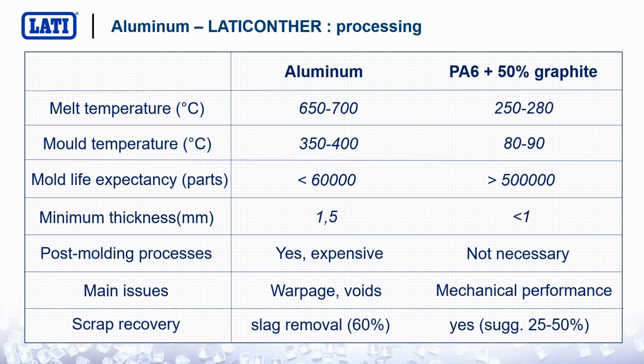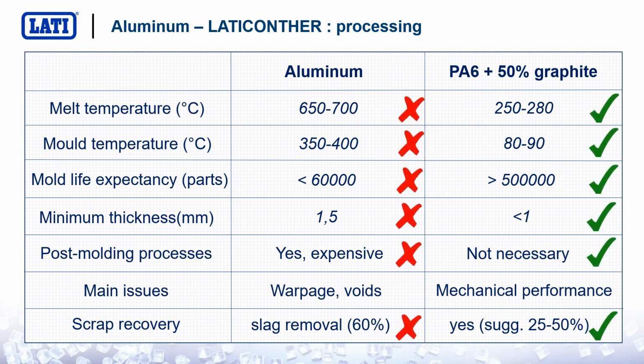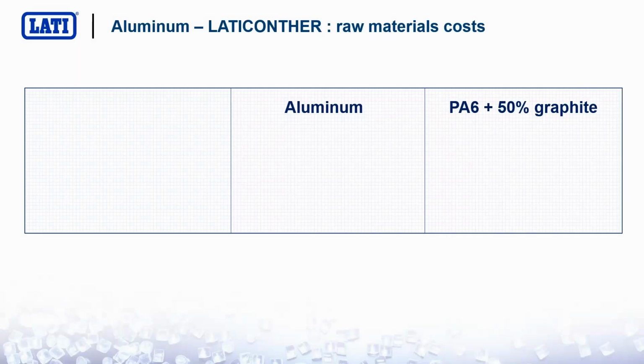And last but not least, talking about scrap recovery, aluminum can be fully recycled, but you have to remove slags from the freshly new melt scraps, and this also impacts the global warming potential. For compounds, you can recycle it 100%, but we normally suggest never to exceed 25 to 50%. So, advantages and disadvantages. I leave to your judgment this chart here.